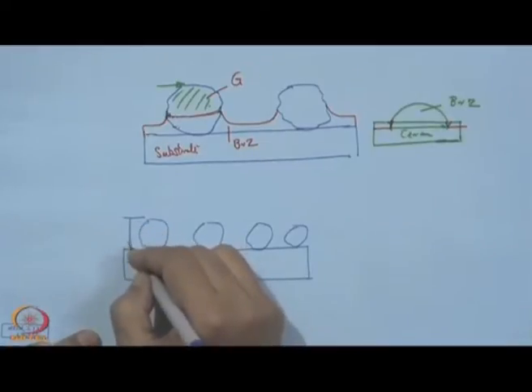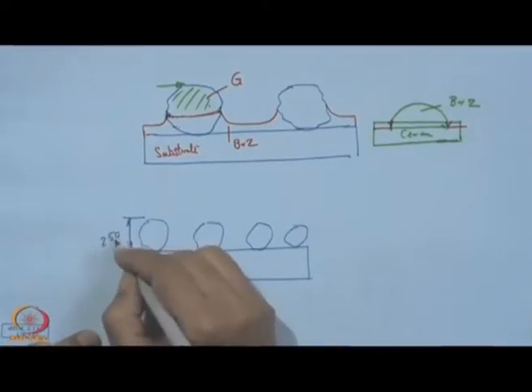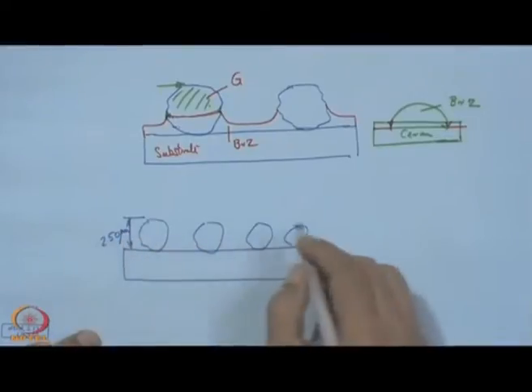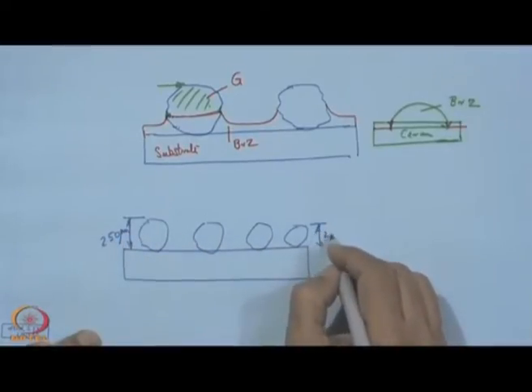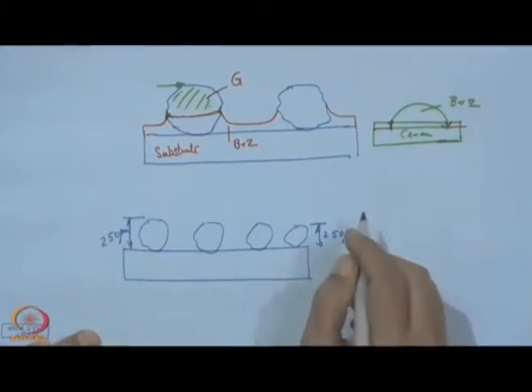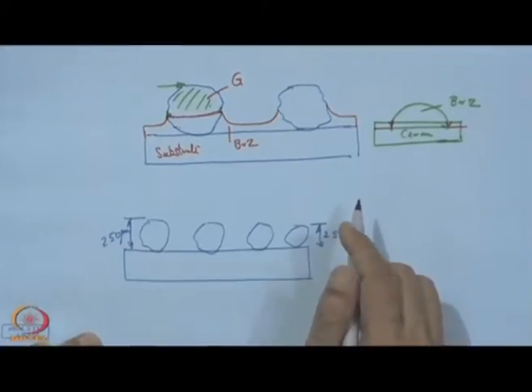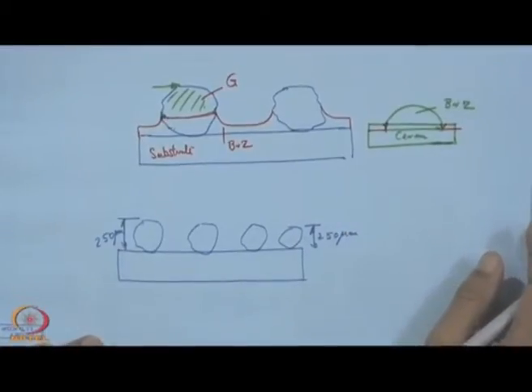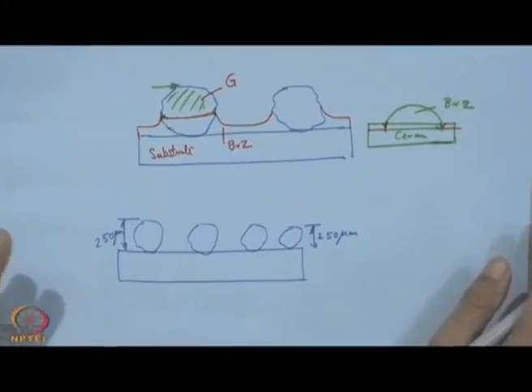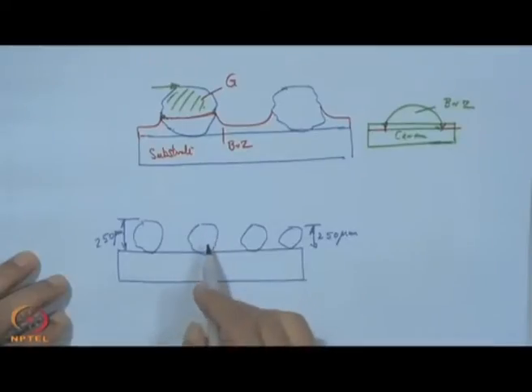Say this grit is 250 micron, a quarter of a millimeter in size, average size. This 250 micron grit has to work without fail, reasonably and adequately to the satisfaction of the user, and over this period a large amount of material has to be removed without damage or fallout of the grit. That is the most important criterion: this grit should not have any kind of premature dislodgement or breakage.